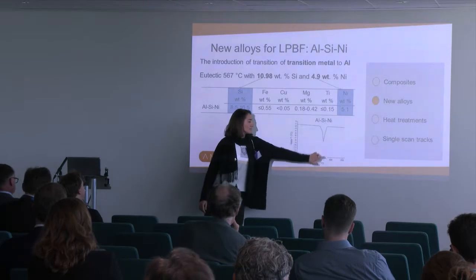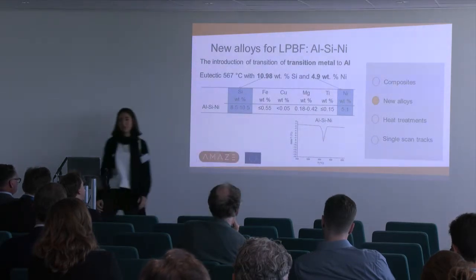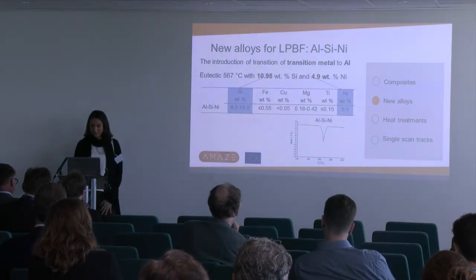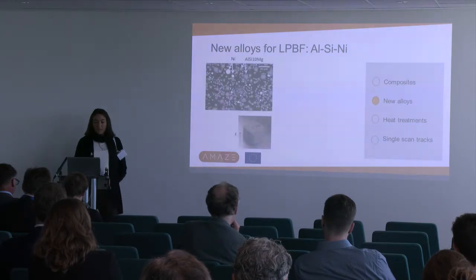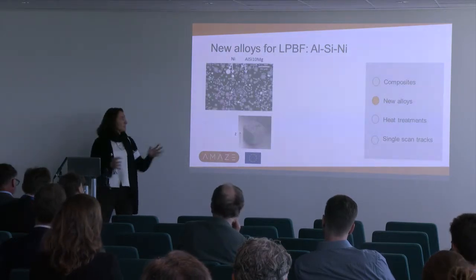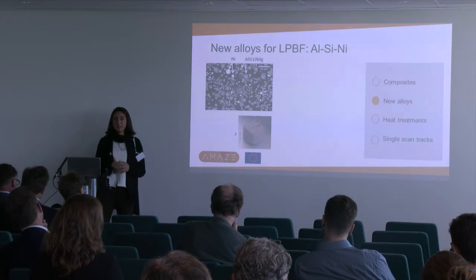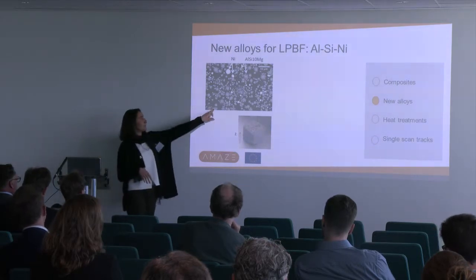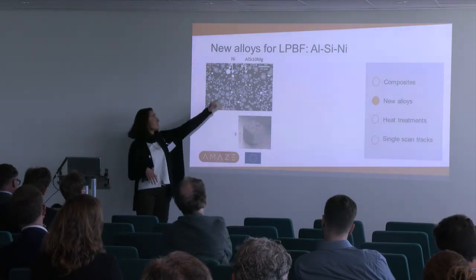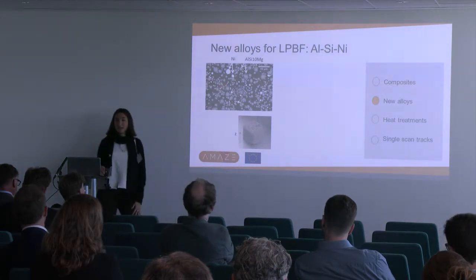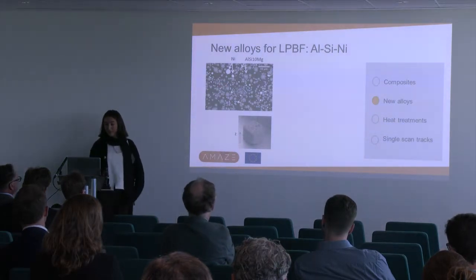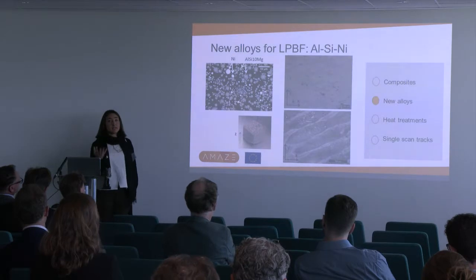We checked the melting range, so we have this graph. This is the melting range, which is even smaller than 50 degrees, so it was really suitable for additive. How we produced it: we took aluminum silicon 10, and we put some pure nickel in it. So we have this powder, the gray particles are aluminum silicon 10, and the white ones, like this one, are nickel. We built samples, and we could obtain dense and crack-free samples.